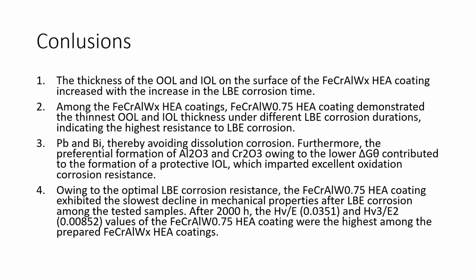Furthermore, the preferential formation of aluminum oxide and chromium oxide, owing to the lower delta G0, contributes to the formation of the protective inner oxide layer, imparting excellent oxidation corrosion resistance. Owing to the optimal LBE corrosion resistance, the material coating exhibits the slowest decline of mechanical properties after LBE corrosion among the tested samples. After 2000 hours, the H/E and H cubed over E squared values of the material coating were the highest among the prepared ferrochromium aluminum tungsten coatings.